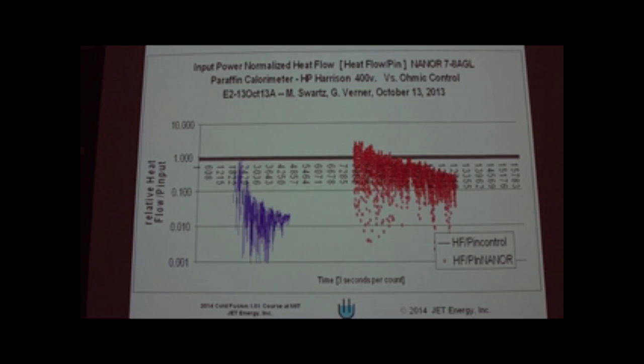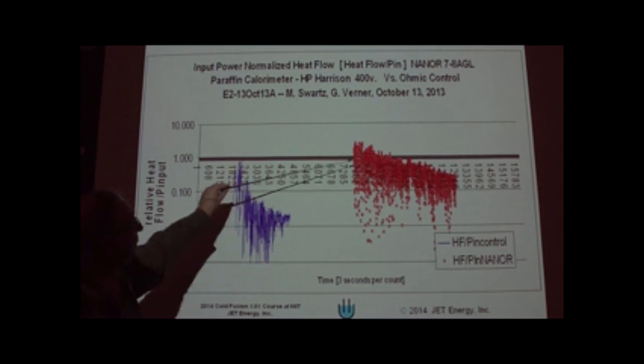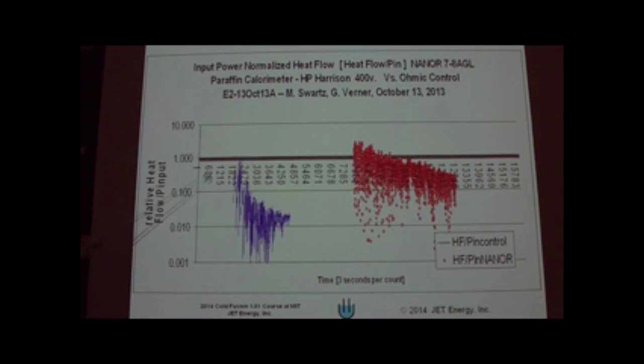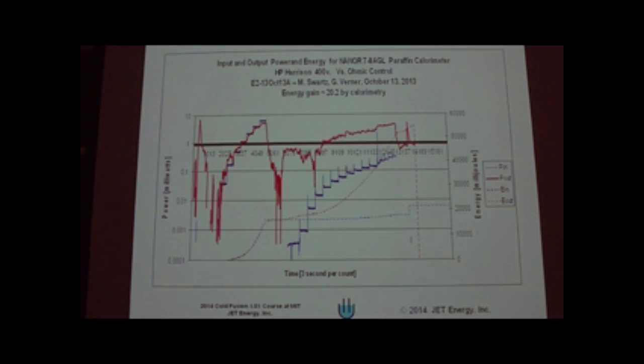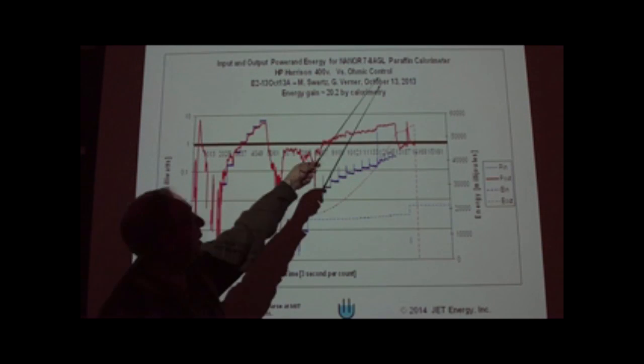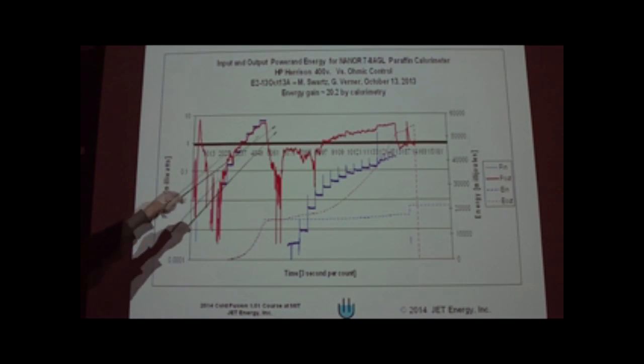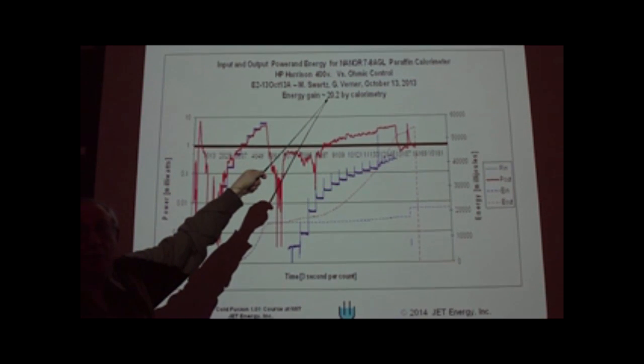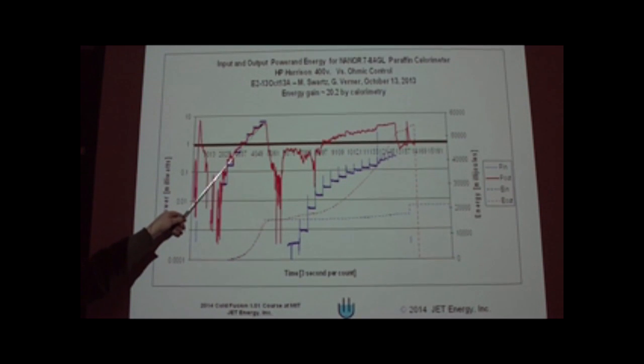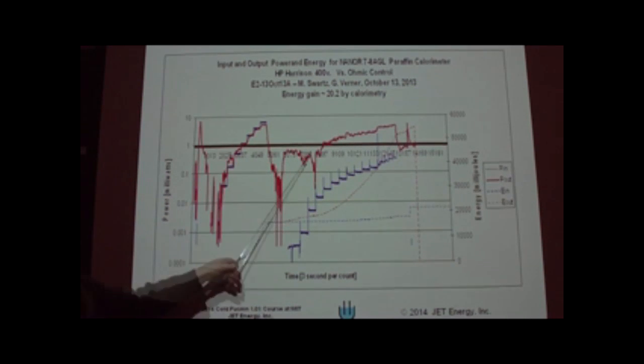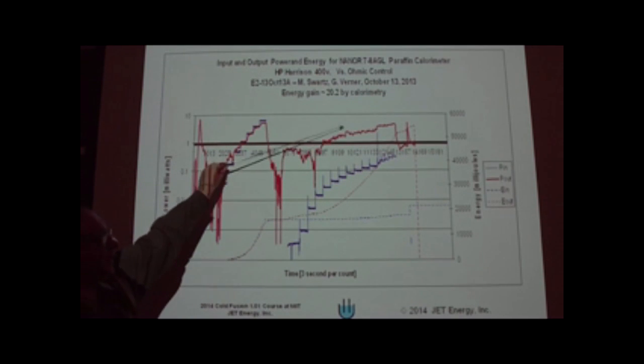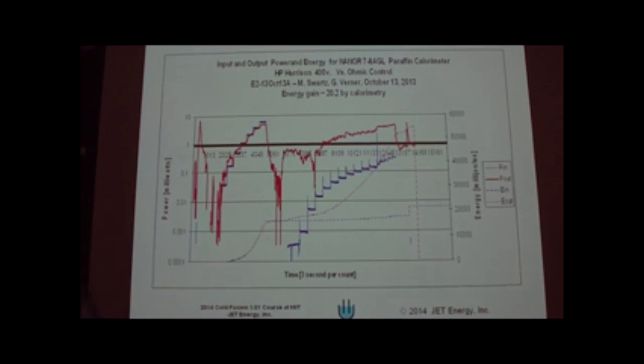You need to understand the optimal operating point manifolds, the fact that there's competitive reactions. And if you do it right, you see it not only with the delta T, here with the heat flow, we're seeing a ratio of what, a decade and a half for heat flow increase. And here's the full bore calorimetry with this nice paraffin calorimeter suggested by Dale. And we have an energy gain of 20. So here's the ohmic control. No matter what level we do, we get a match. When we treat here, we see a great energy gain and therefore a superlinear rise.